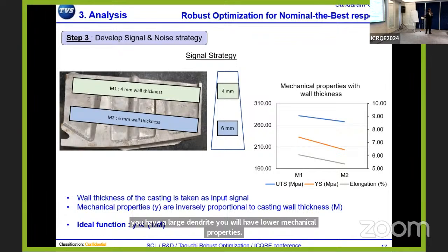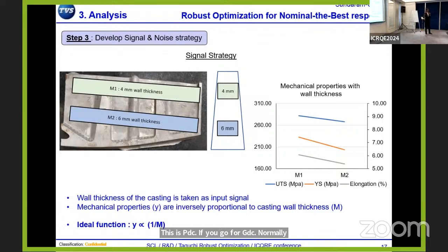This is PDC. If you go for GDC, gravity die casting, normally the solidification time is a little big, the solidification time 100 seconds, 150 seconds. So there the dendrites will be very long, and you cannot get these mechanical properties. But in PDC, the solidification time is 10 to 20 seconds. So that is why we are getting higher mechanical properties in HPDC. Even in that, between this wall thickness, there is a change in the shape of the dendrites.